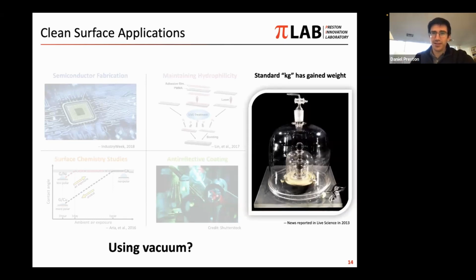And an interesting anecdote here, a story that you can look up in the news, is that the standard kilogram has actually gained weight over time. The reason for this is because there's a thin layer of adsorbed contaminants on the surface. They probed this and found that some of them are mercury-based. Most of the contaminants are carbon-based. And so there are some hydrocarbons from the air that make their way into this sealed chamber, even under vacuum, and stick to the surface of the standard kilogram and change the value.